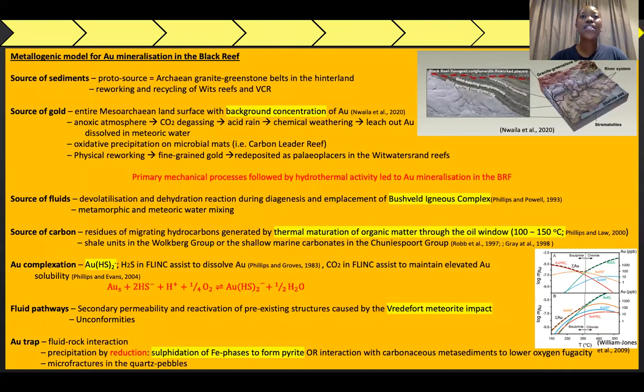So a more likely source is the entire Meso-Archean land surface of the whole Kaapvaal Craton envisaged by Nwaila et al. 2020. This land surface contained background concentrations of gold. In an anoxic environment with CO2 degassing from high volcanic activity, acid rain formed and caused chemical weathering, which leached out gold from its precursor host and transported gold as a dissolved species in meteoric water. The gold was precipitated out of solution by oxidation when the fluids were in contact with photosynthetic cyanobacteria, seen as the microbial mats. This is the reason why the Carbon Leader Reef has the highest gold content in the Carletonville goldfield, gold that is associated with carbon seams.